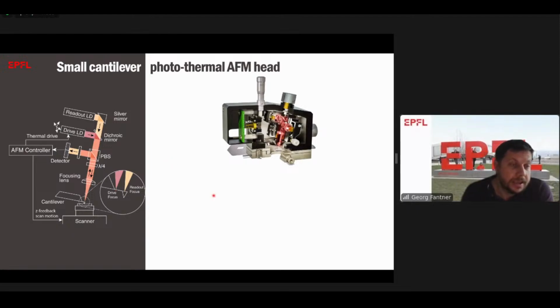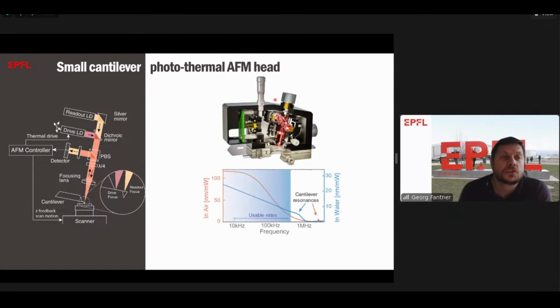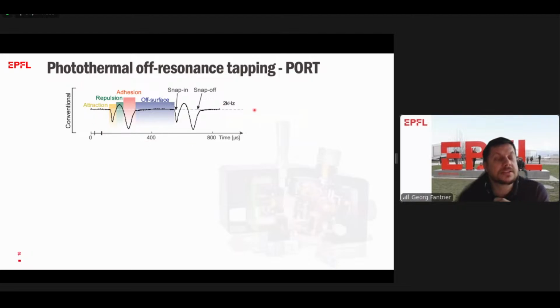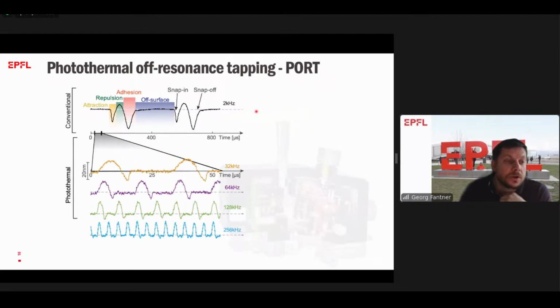This is actually a plug-in replacement for the Veeco or Bruker Multimode AFMs. So if that's one of the microscopes that you have, you can just take the normal AFM head off and put this head on, and it's plug-in compatible. And with that, we can now operate this off-resonance mode instead of at 2 kilohertz, which is a typical off-resonance frequency that you can get with a commercial instrument. We can go to several hundreds of kilohertz, and the most recent data by our student is even up to 1 megahertz in this off-resonance mode.